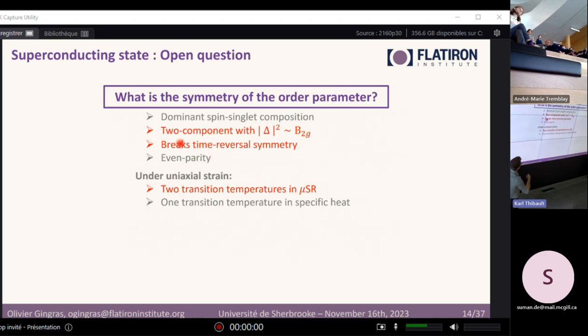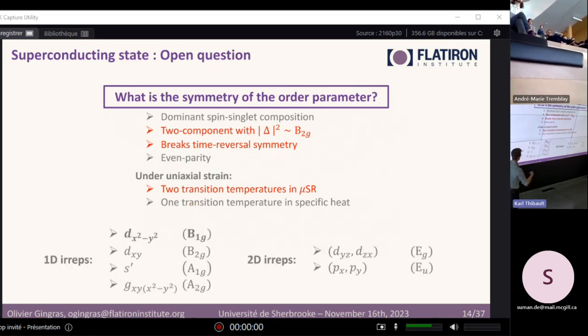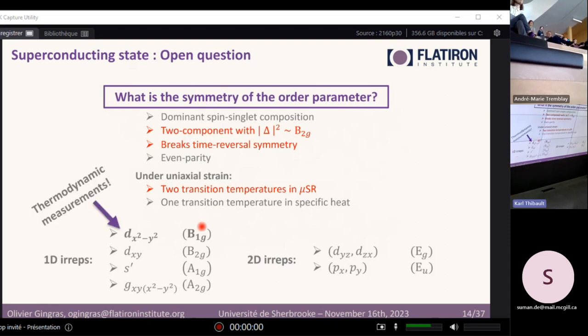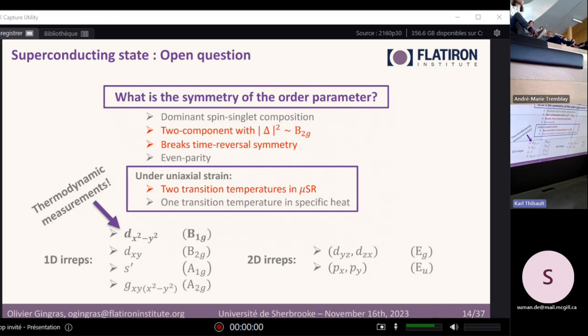And it appears to be even parity due to the rise of Tc under uniaxial strain. But there's this tension between the two transition temperatures in μSR and the one transition temperature in specific heat. So there's a lot of theory work that was done to propose candidates. In particular, here you have this d-wave state that works with all the thermodynamic measurements. But there's always this tension of trying to explain these two experiments at the same time. In this standard way of thinking about the problem, these two things are very inconsistent.